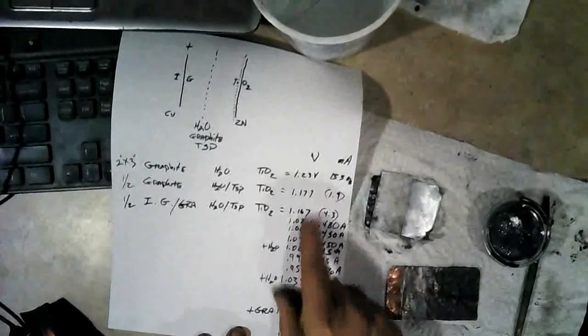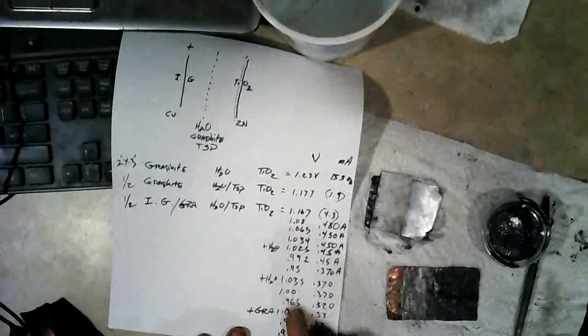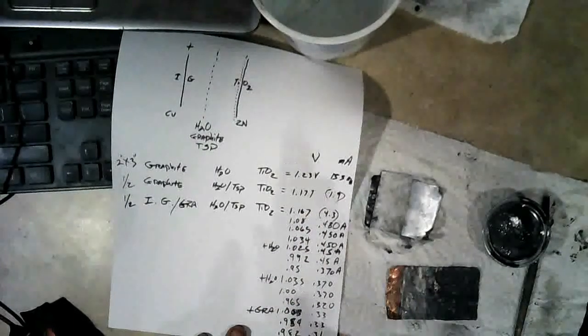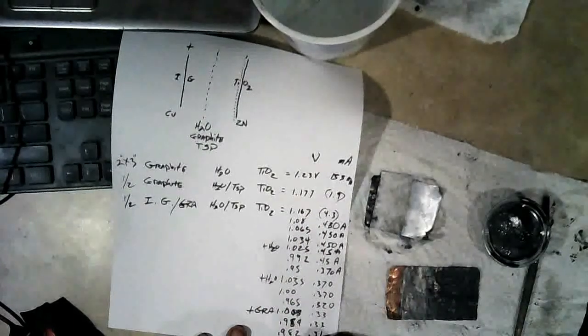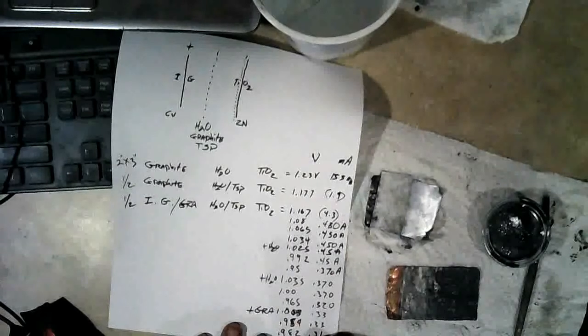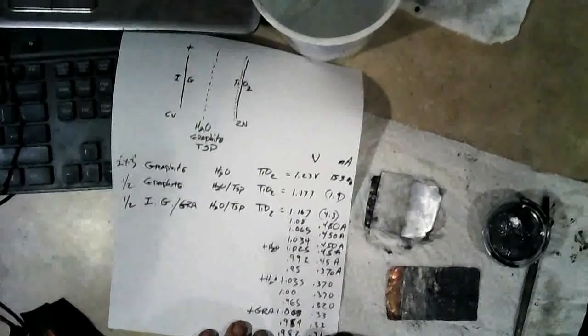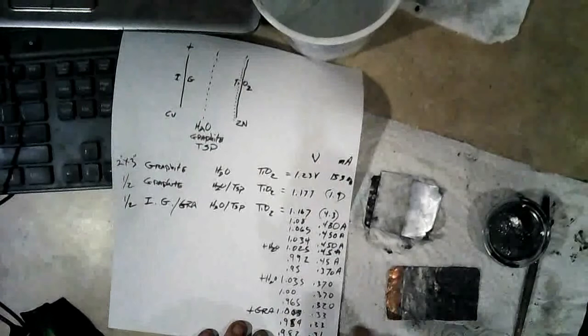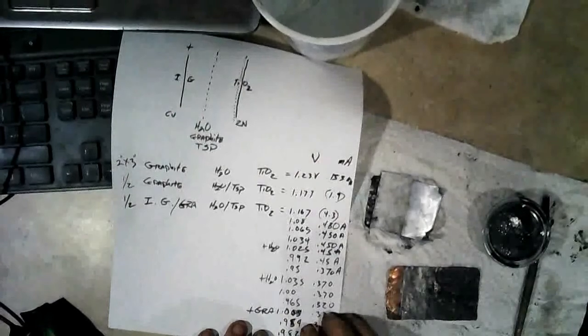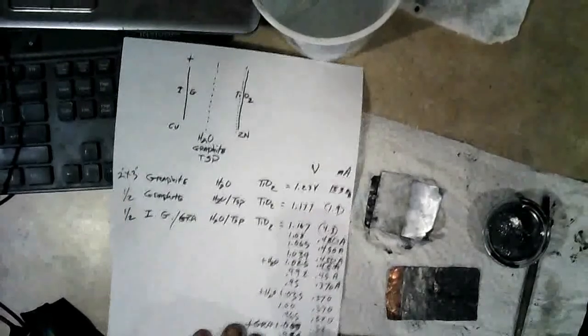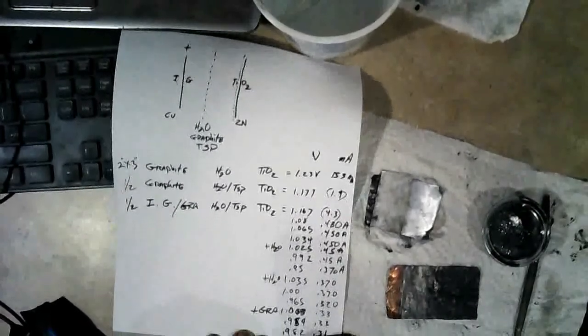It dropped its voltage the whole way too. That could be somewhat from water loss, or it could be maybe where the membranes were breaking down from the higher current load or something.